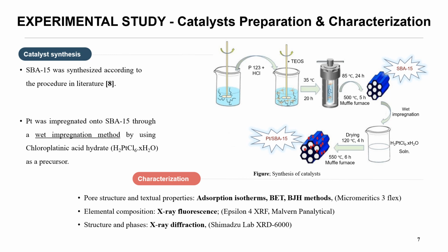The metal loading was also achieved by a wet impregnation of platinum precursor. In this method, SBA-15 was dissolved in a chloroplatinic acid solution and then kept for 24 hours. Subsequently, the material was dried and calcined for 6 hours at 550 degrees Celsius to obtain platinum-loaded SBA-15 as shown in the figure. Characterization of the prepared catalyst were done using XRD, XRF, and BET techniques.